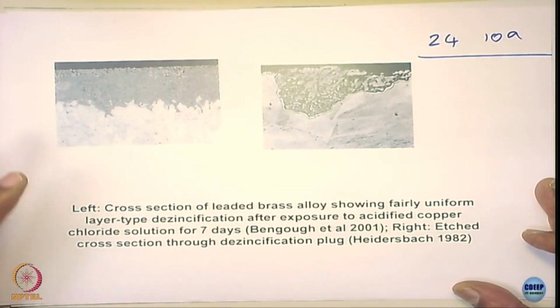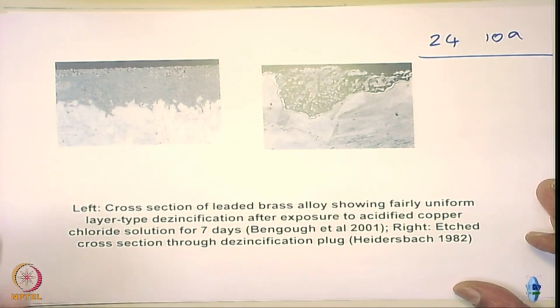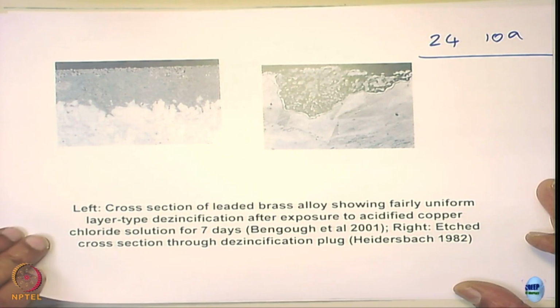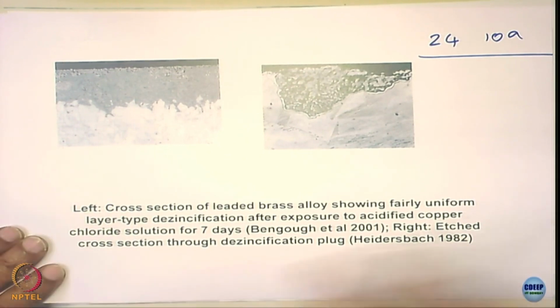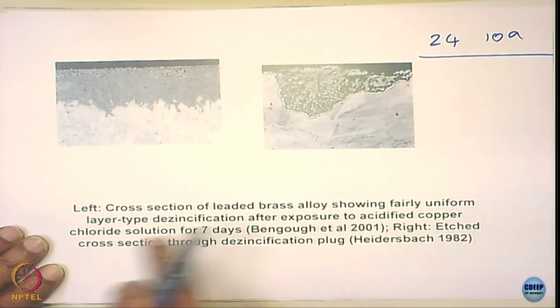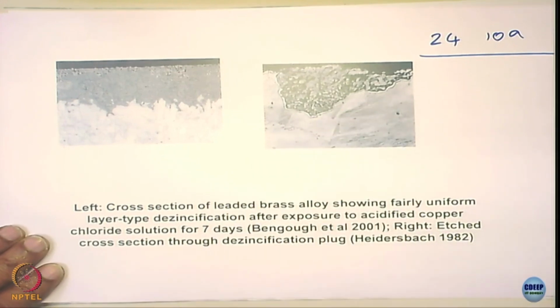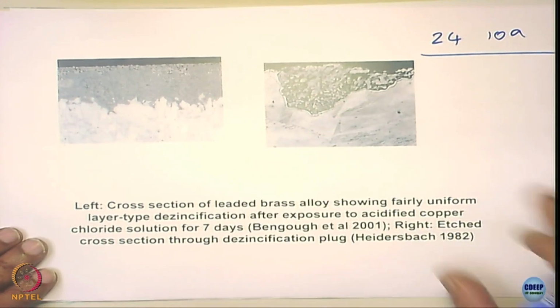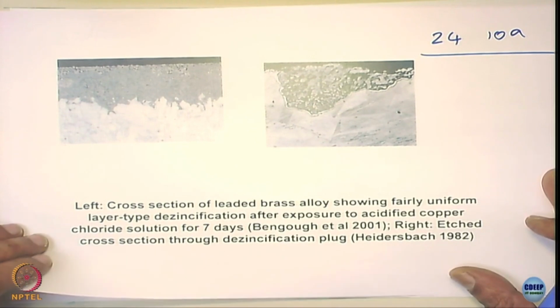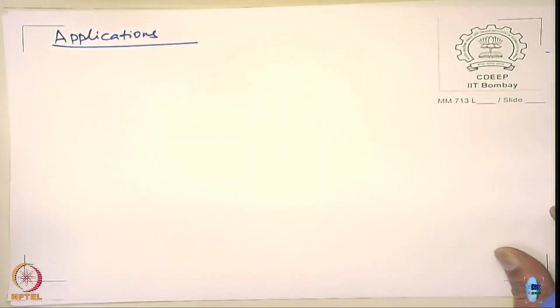So these are the real problems that happen, but fortunately dealloying is not as fast as pitting corrosion and all, but yes, it does affect over years. And in this case of course this is an accelerated one, in acidified copper solution, so 7 days only, but in practice it may take a couple of years to get the dealloyed layers on the surface.